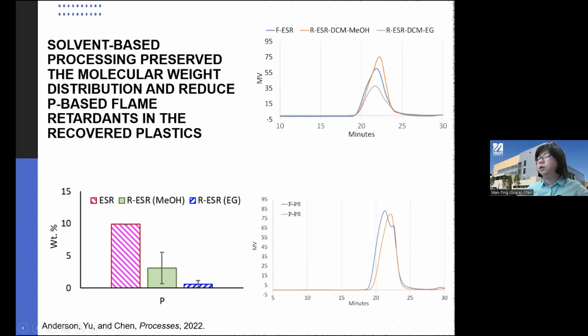And what you see on the right-hand side here is the molecular weight distribution of the polymer. For a polymer, the most important thing is, you can imagine a polymer like a very, very long noodle. At the end of the day, once we clean and extract this polymer, we want the length of the noodle to be very, very similar. We don't want it to be chopped down. If they are being chopped down, they are not valuable anymore. In fact, we reduce their value. So we want to get the long noodle back as it is in terms of its length.